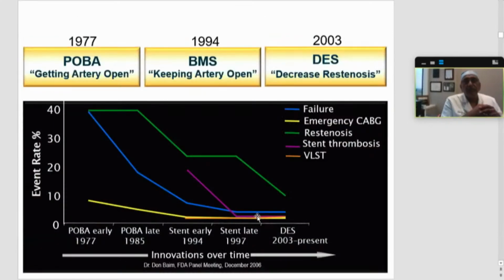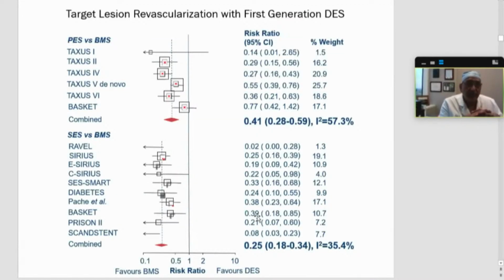And as you draw a timeline from 1977, from the very first day balloon angioplasty was performed, to the 2000s, you can actually see that everything got better. The failure where there was immediate occlusion almost went away. Emergency bypass surgery definitely went away. The restenosis rates dropped dramatically from 40% to less than 20%. Stent thrombosis reduced, as well as VLST. And as time has progressed, we continue to keep on getting better.